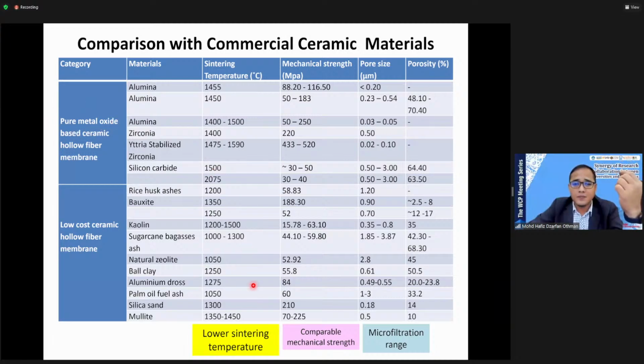In terms of the sintering temperature, you can see here that it is much different, about 200 to 300 degrees Celsius different. And for the mechanical strength, although some of the materials have quite low mechanical strength, some of them like bauxite, silica sand, and also mullite have almost comparable mechanical strength with pure metal oxide. And the pore size of the membrane is almost similar, which falls under the microfiltration range.